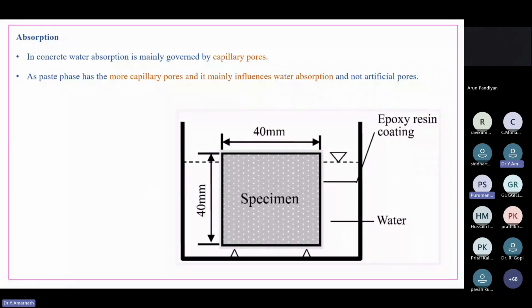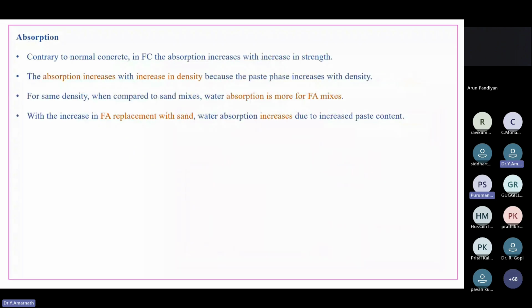Now, coming to the absorption property of foam concrete, contrary to normal concrete, in foam concrete the absorption increases with increase in strength. Usually in normal concrete, as the strength increases, the absorption decreases. But in foam concrete, at lower levels, there is an artificial pore system present, which disconnects the capillary interconnectivity, and the absorption is lower at lower strengths. So please observe this particular statement: contrary to normal concrete, in foam concrete the absorption increases with increase in strength. As strength increases, absorption increases in foam concrete. But that is not the case in normal concrete. In normal concrete, as strength increases, absorption decreases.